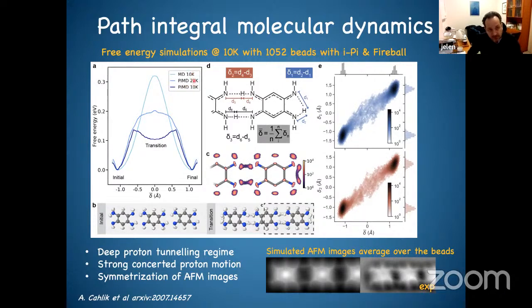Now here the temperature is very important. And as you go down, what you see is that this barrier is no longer the classical Gaussian shape we know, but it starts to evolve this dip in between the barriers. So the barrier is dropping, but of course there are also new minima which you will find, and that's what people call the signature of proton tunneling. So it means that the proton is no longer on one side or the other, but also has a certain probability to penetrate inside. You can see it already here, that the proton is sampled somewhere in between. And indeed, in this phase transition, this transition state, you see it happens here.